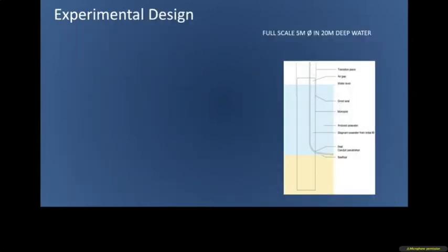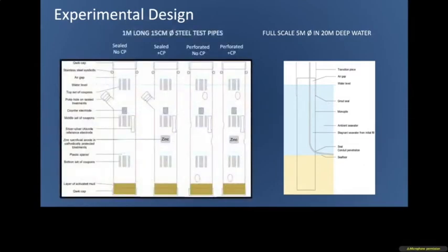So experimental design. We're dealing with huge structures. Full scale, maybe a 5-meter diameter, 20-meter water depths. And so what we did is we scaled this down, and we took 1 meter long, 15 centimeter diameter steel pipes. We capped them top and bottom. And in the bottom cap, we put local sediments to imitate the seafloor bottom in the monopiles. And we took 4 of these pipe sections. One was sealed with no cathodic protection to represent the initial offshore monopile design, and one sealed with cathodic protection, which was the refit to counteract corrosion observed in the structures.